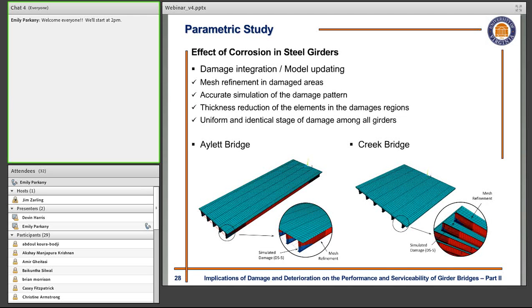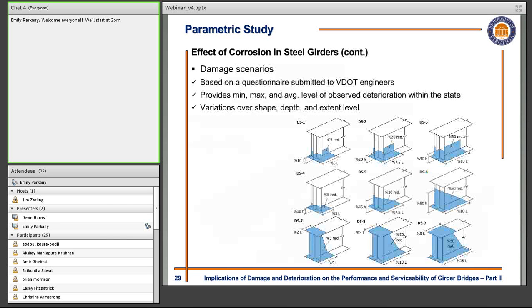And the damage modeling was in the format of reduction in the thickness of the elements because of the existence of this corrosion. In real practice, corrosion between different girders might be different because of the environmental condition or the level of the attack of the corrosion. But in this case, we assume a uniform and identical stage of damage for all of the girders at either end of these simulated bridge superstructures. Regarding the damage scenarios, as I mentioned before, we prepared this questionnaire and we asked the engineers to provide us the minimum, maximum, and average level of observed deterioration within the state.